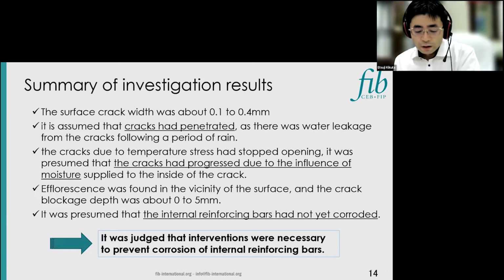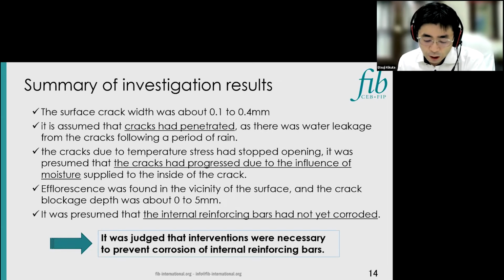Detailed investigation revealed that the cracks had penetrated and that reinforcing bars had not yet corroded, and so on. Also, it was presumed that the cracks had progressed due to the influence of moisture supplied to the inside of the crack. Based on these factors, it was judged that interventions were necessary to prevent corrosion of the reinforcing bars.